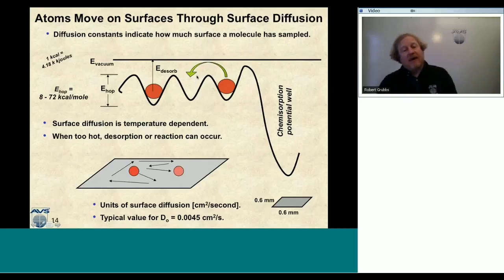And so if the temperature is too hot, then this molecule on the surface can actually desorb back into the continuum above the energy of the vacuum, or it could actually undergo a chemical reaction and fall into this chemisorption well and make a chemical bond with the surface. So surface diffusion is temperature dependent. If it's too hot, we can desorb molecules. We can also cause reactions to occur. So when we're talking about atomic layer deposition, we obviously want reactions to occur. So we need to have the temperature right in order to do that.